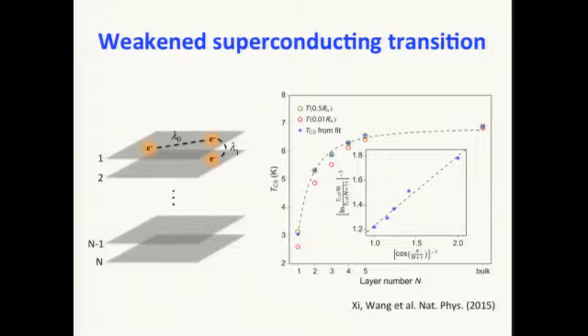Another way to see that this is actually a pretty good model to describe the decrease in TC is to plot the TC in this strange way, log of something, and then 1 over the cosine of pi over n plus 1, n is the layer number. It follows a pretty good straight line for the data. So it provides a pretty good support for the interpretation using this model.